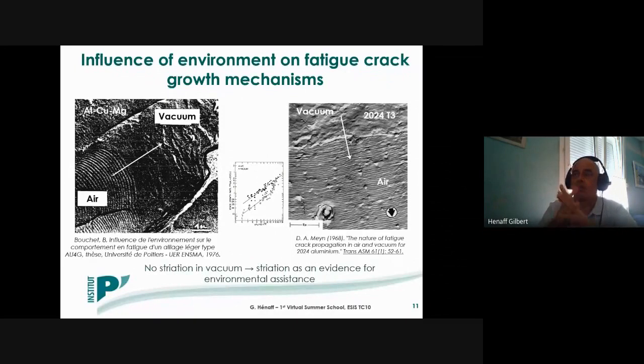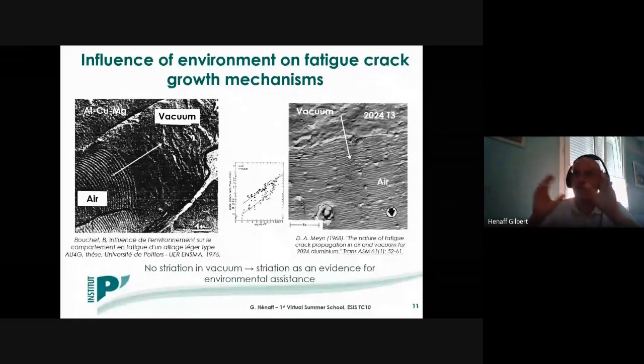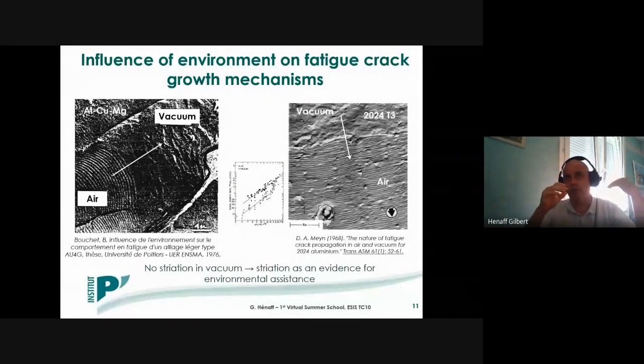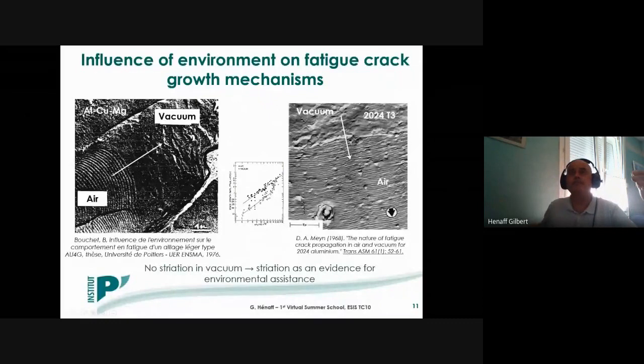Another evidence of the influence of ambient air as an active environment is when looking at the fracture surfaces, here in the case of an aluminum copper magnesium alloy. And in these experiments, we changed the environment during propagation. So for instance, on the left-hand side, the propagation first takes place in air. And at this stage, we switch to vacuum.